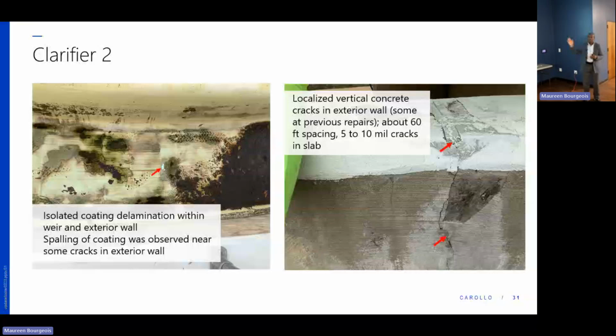For the lab testing for this one, we did 8 cores, we examined them. And so concrete capacity there, we looked at a compressive strength, which we defined earlier. That's between 6,000 in the 6,000 ranges. Again, well above our 4,000 minimum average that we typically see for structures such as this, and that was also documented. Carbonation here was negligible, and then chloride also was negligible, and so that's good for this structure.